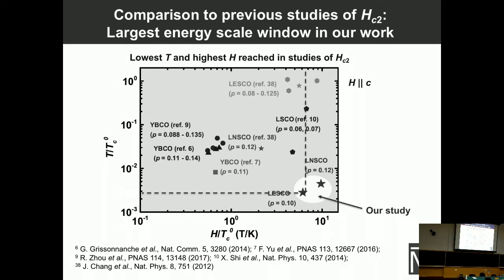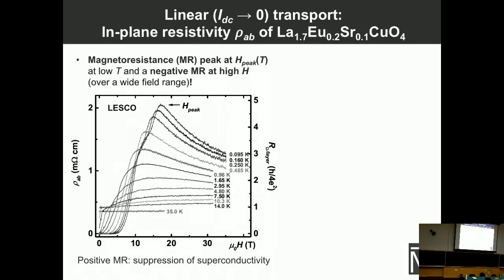Whereas the previous study on exactly the same material explored only this window of parameters. Okay, so let me show you some data. First we measured linear transport, or transport in the zero current limit, in particular in-plane magnetoresistance. Here are the raw data, and I will show mostly data for this material, but they are qualitatively the